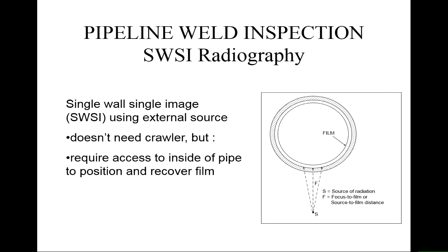And we'll look a bit more at other types of defects later on. You can't always get what you want. You can't always put a crawler down a pipe. Sometimes you can get somebody in, a short distance away from the front end of the pipe, to put some film over the weld, and then you can use an external source to show up the defects.